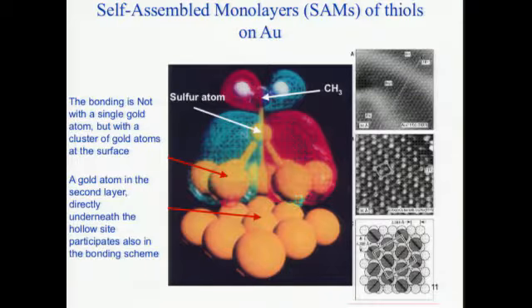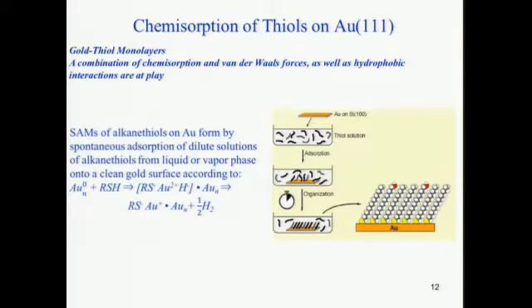And this actually is showing all of that. It's showing the spacing between the gold atoms. It's also showing the overlayer structure of an alkane thiol monolayer relative to the gold surface. And this line here actually represents the orientation of the alkane thiol backbone relative to one another. And so those are all important. I think the main thing I want to show here is that there's a driving force. Whenever you have a monolayer, I told you that there are specific interactions. In the case of alkane thiol, it's the gold-thiol bond and the van der Waals interactions of the alkane backbone. And so how does it work?